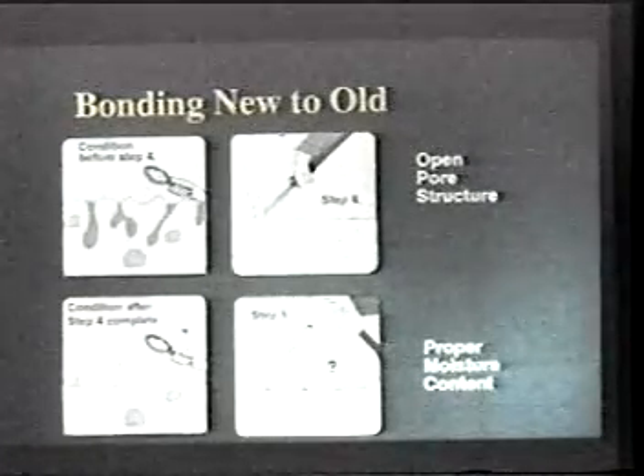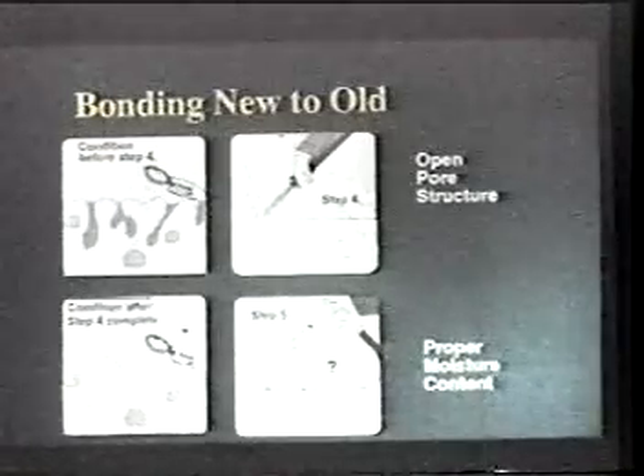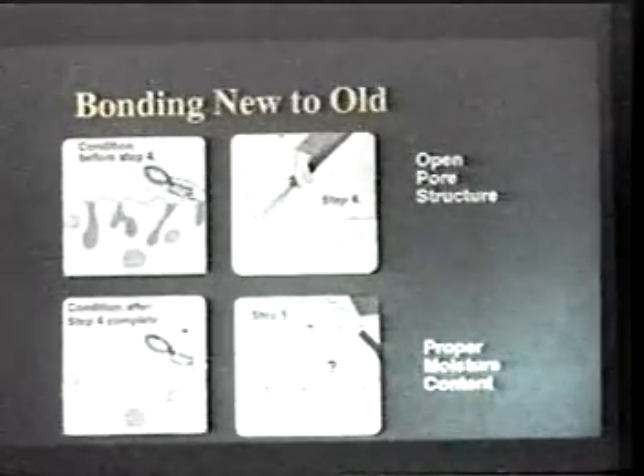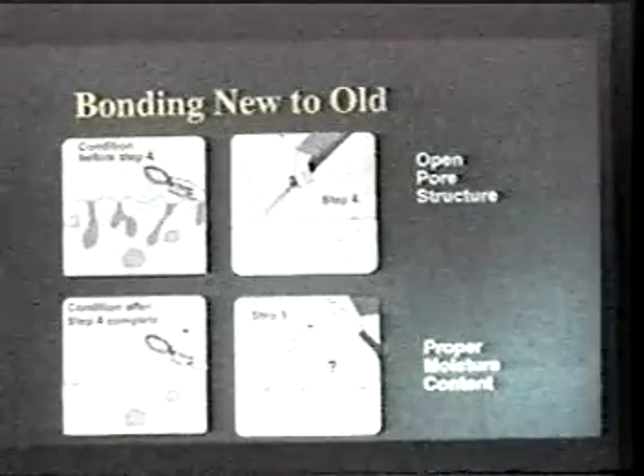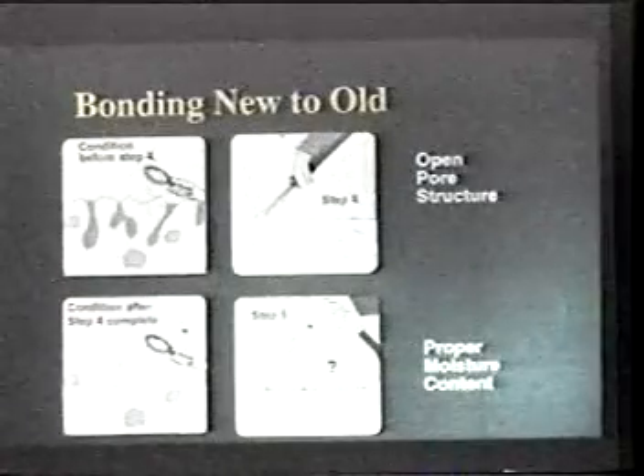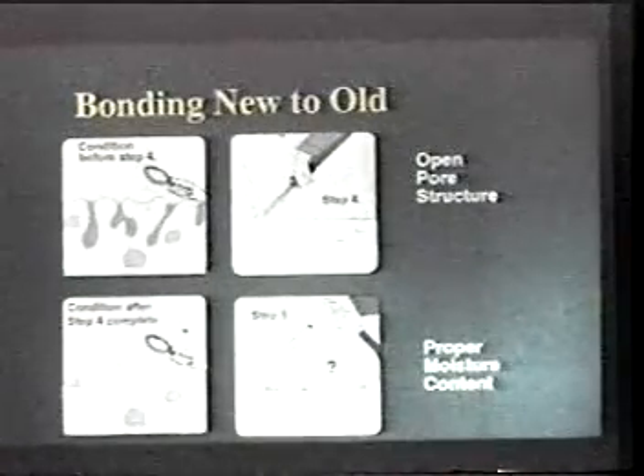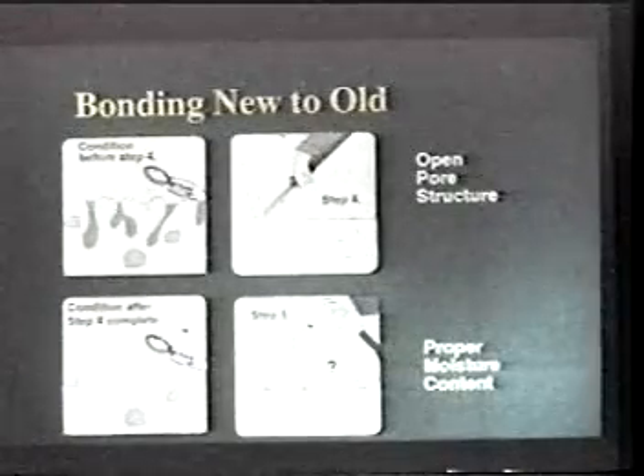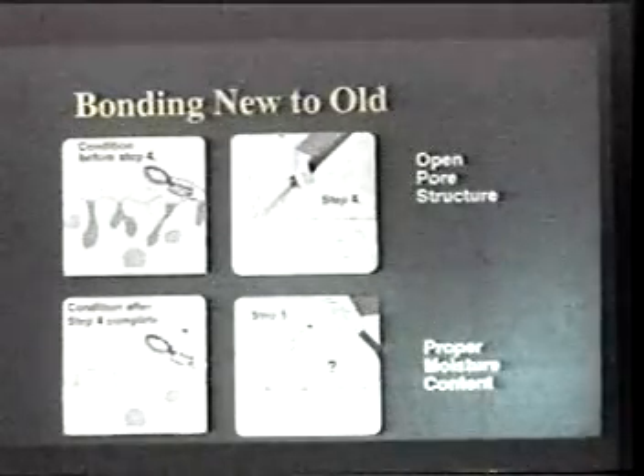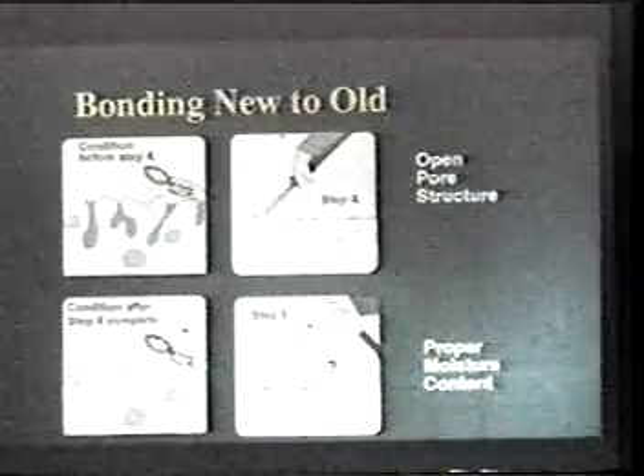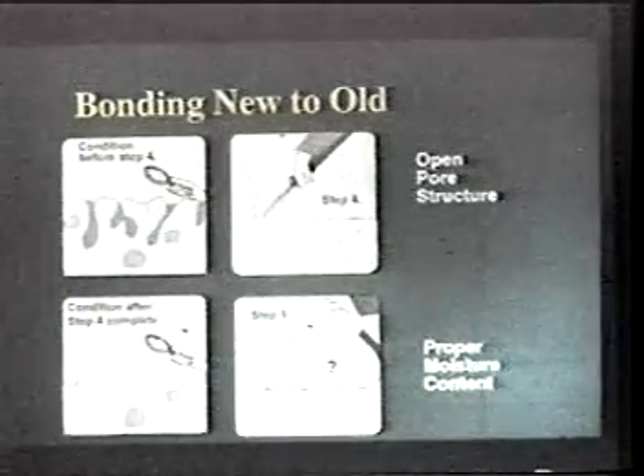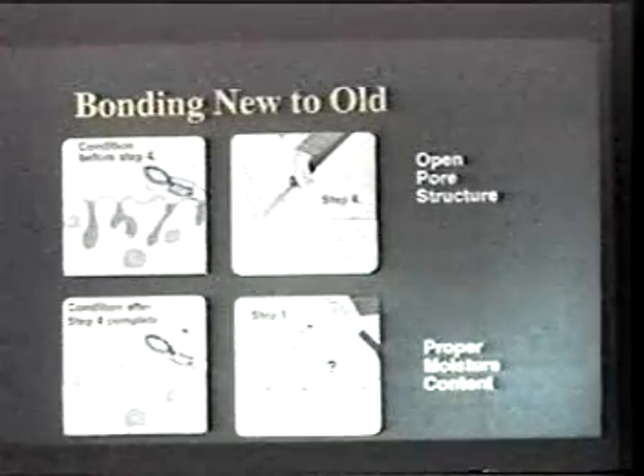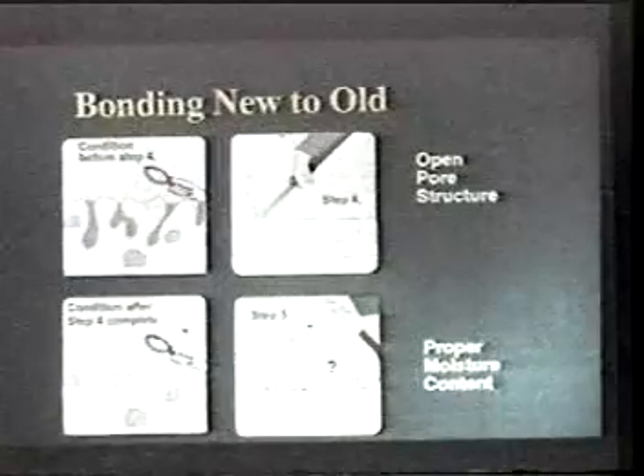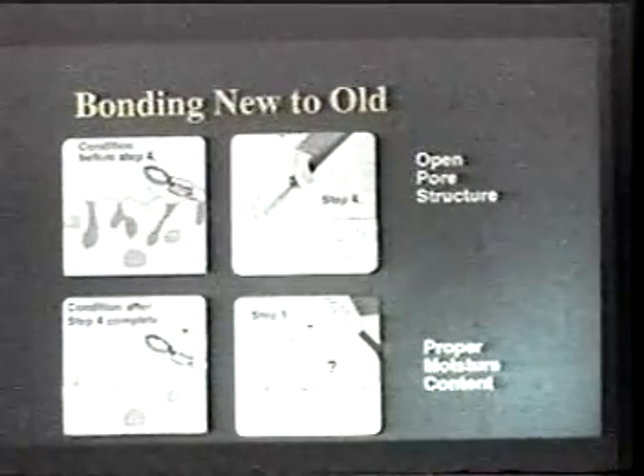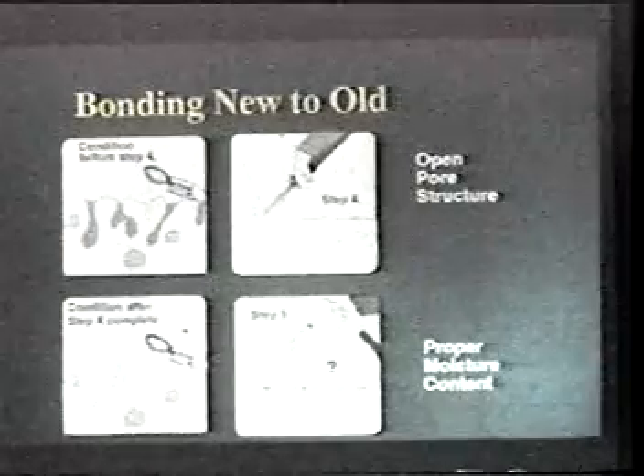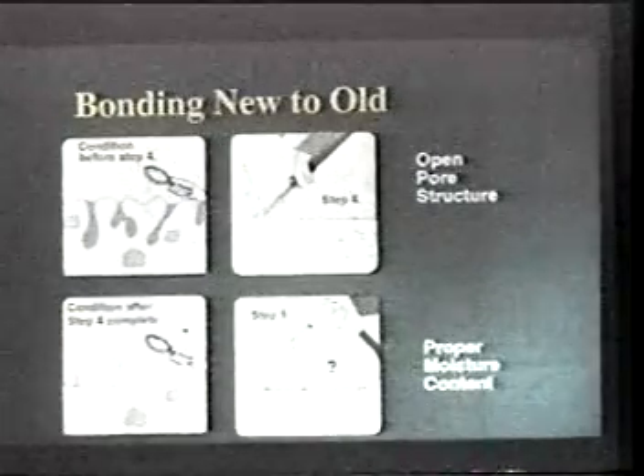How do we find out which one is the best? Sometimes it is bone dry, sometimes it is slightly sprayed. It depends very much on the material in the substrate. It depends to a large degree on temperature and humidity at this time. So what's the way? If you have time and money and you want really to achieve the best possible result, you have to run 3 different pilot projects on small areas, 3 different moisture conditions, and then run this pool of tests and find out which one is good.